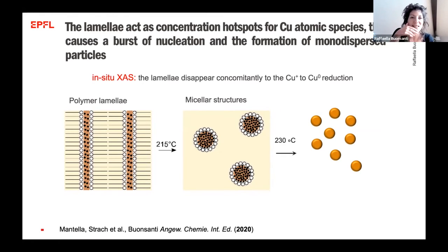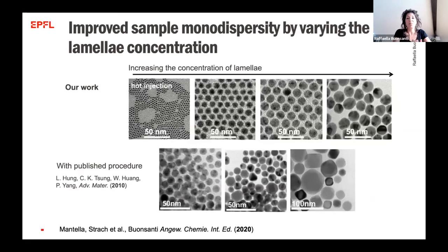And so we suggest here that these polymer lamella are acting as concentration hotspots for the copper atomic species, and they cause a burst of nucleation and eventually the formation of these monodispersed particles. Now, having learned that these polymer lamella are the intermediates behind the synthesis of these copper nanoparticles, what we did was to synthesize the polymer lamella and to use them directly in the flask to change the concentration to obtain these highly monodispersed spheres, which possessed high monodispersity compared to a previously reported procedure.